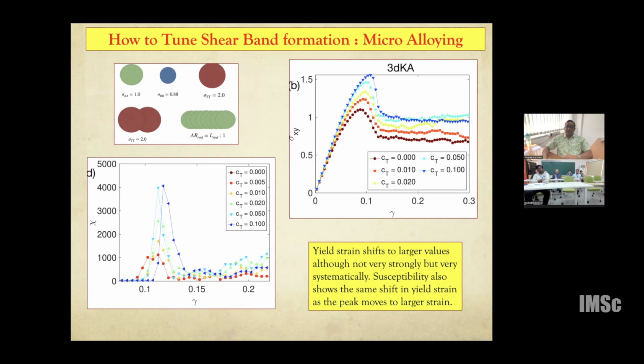We tried this concept and studied the yielding process in a setup where you introduce particles which are twice the size of your host particle. This is demonstrated in this figure in the top left corner. We took particles of twice the diameter and changed their concentration. We do see that the yield point moves to larger strain, so it has some pinning-like effect, but it's not fully what you can get in random pinning. But it produces some effects which we feel are a signature of a pinning-like effect.